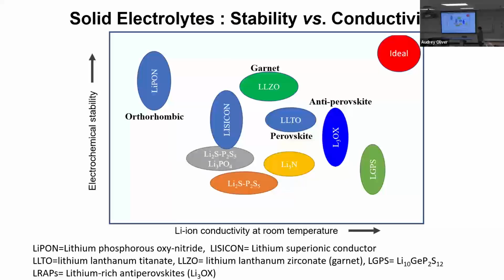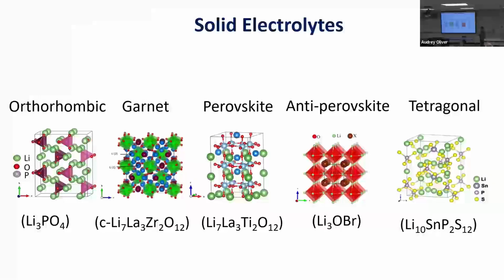So what you can see here is electrochemical stability versus ionic conductivity. What we want is right here, high ionic conductivity and very stable, but none of them are there, right? So what we did, we looked into this one, a high ionic conductivity material, and doped that system to increase its stability. The other way we tried was this one, to increase conductivity. We couldn't improve this one much, but we could do something here. Okay, so first in DFT, we need the structure.